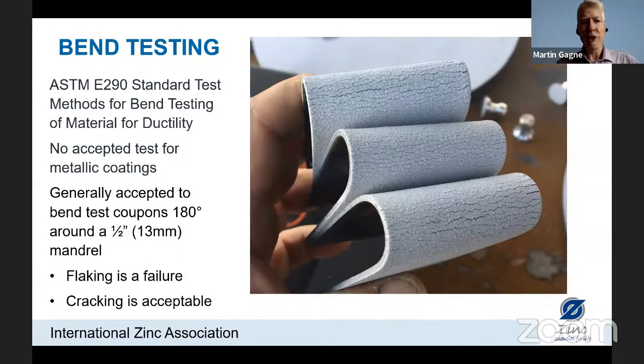There is a standard bend test for measuring ductility of materials, but there is no accepted test for metallic coatings. So there is a generally accepted practice to spray onto a steel coupon and do a 180 bend test around a ½ mandrel. We can see some cracking here. Cracking is acceptable. It is flaking that registers as a failure in the bend test.